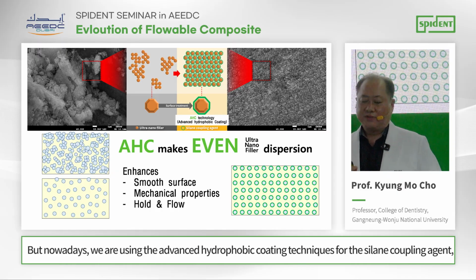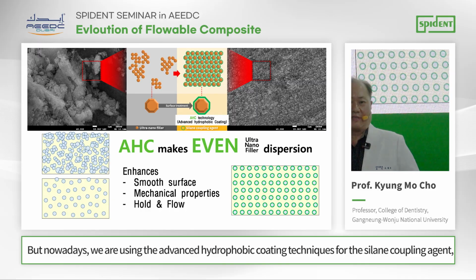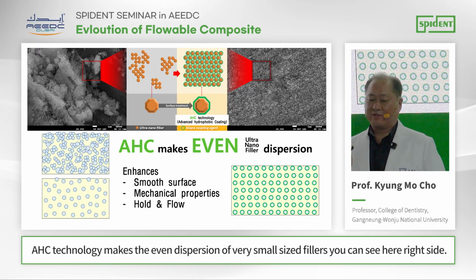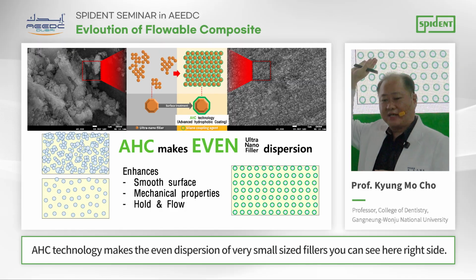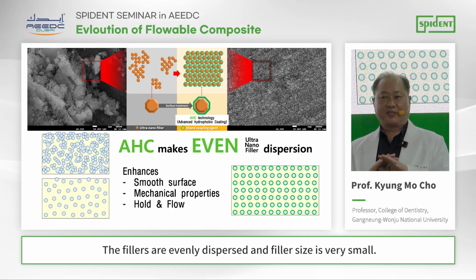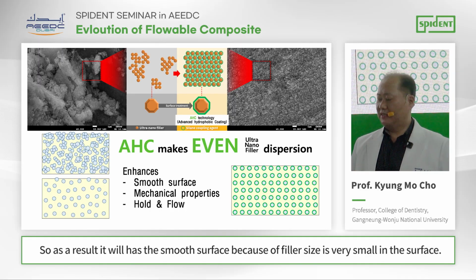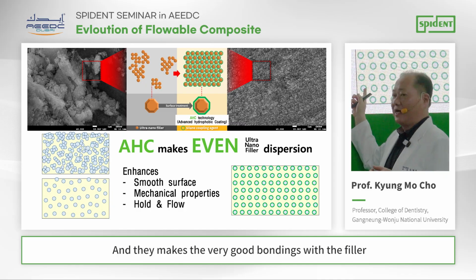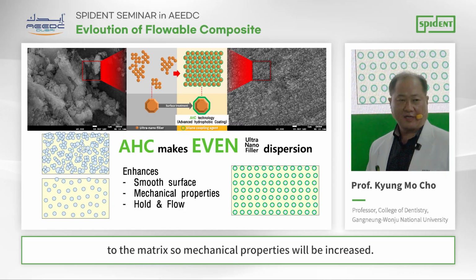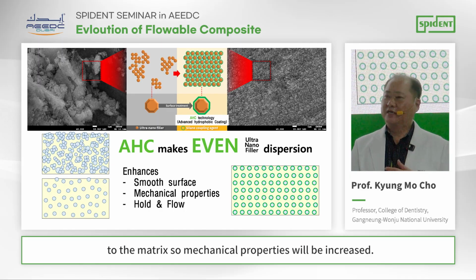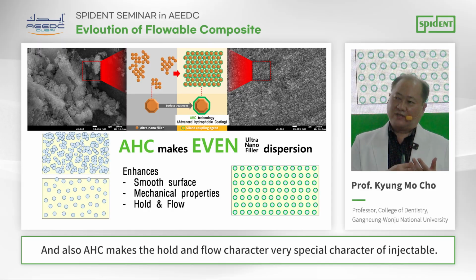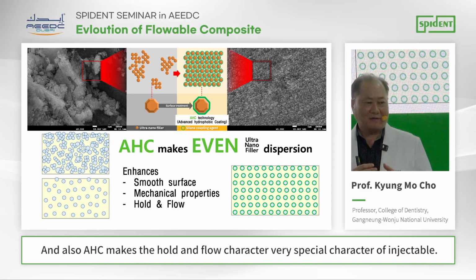But nowadays, we are using advanced hydrophobic coating techniques for the silane coupling agent, AHC Technology. AHC Technology makes even dispersion of very small fillers. As you can see on the right side, the fillers are evenly dispersed and the filler size is very small. As a result, it enhances the smooth surface because the filler is very small. It also makes very good bonding of the filler to the matrix, so mechanical properties are increased. And also, AHC gives Injectable its hold and flow characteristic, a very special characteristic.